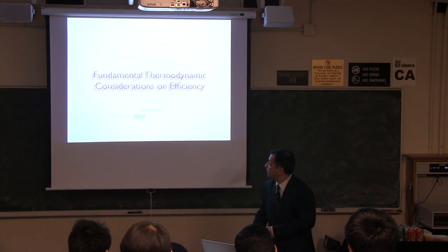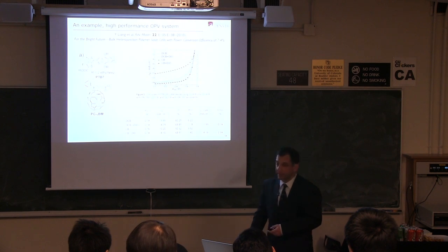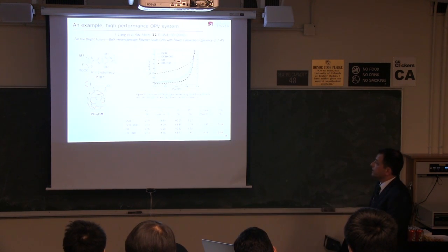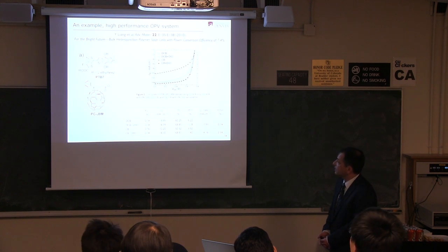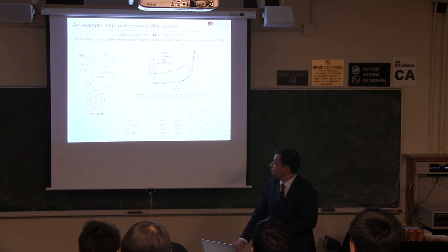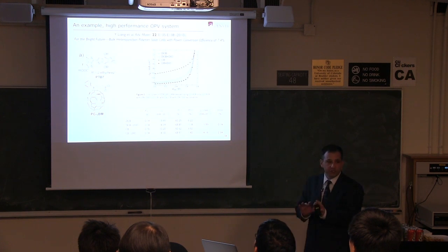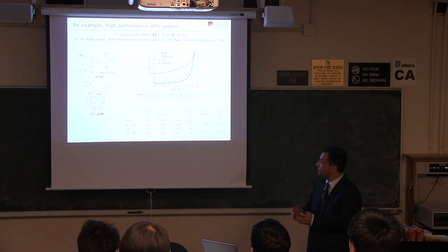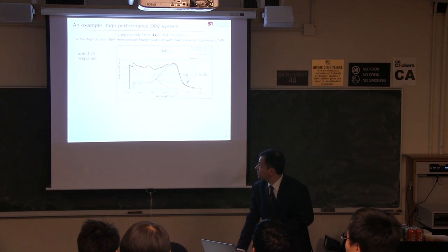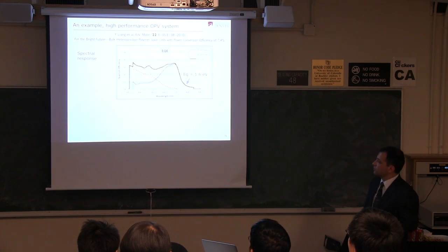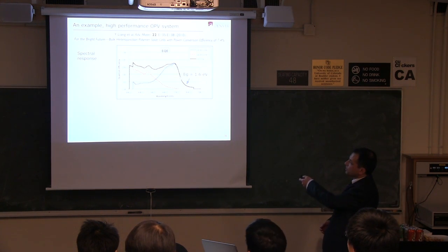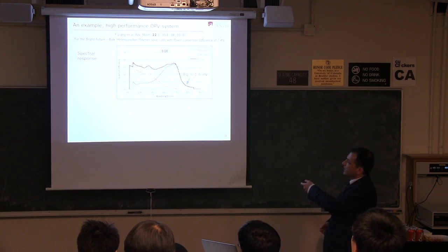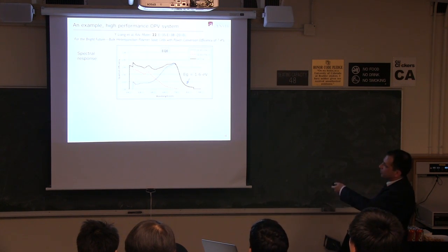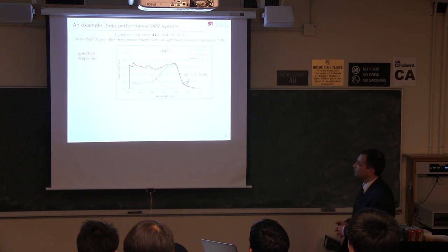And let me just go into a few specifics about thermodynamics. So one is about the losses that are in the device. And I want to, again, focus on this material, PTB7. We're going to use this as a test case to examine all of the thermodynamics of. So first of all, what's the spectral response? And first of all, these materials have a resonant absorption. So the blue curve here is the absorption of the polymer. And it is unlike an inorganic semiconductor that has a sharp band edge and then is just flat all the way across. But we could define a band gap of about 1.6 electron volts.